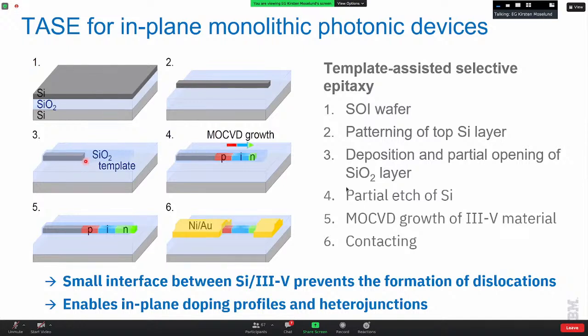So it's similar to nanowire growth in the way that if you keep your nucleation seed small, let's say on the order of 100 nanometers roughly, then you avoid any dislocations and you only get local defects that terminate within a few nanometers here. Then afterwards, we've grown the structures. You can either keep them as they are, or you can strip the oxide depending on if we're making a transistor or the type of device, and then we contact them as usual.